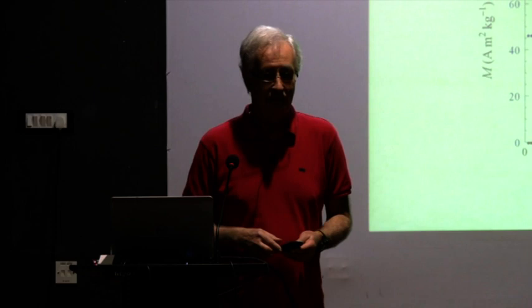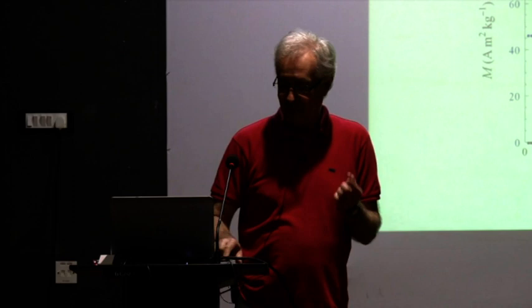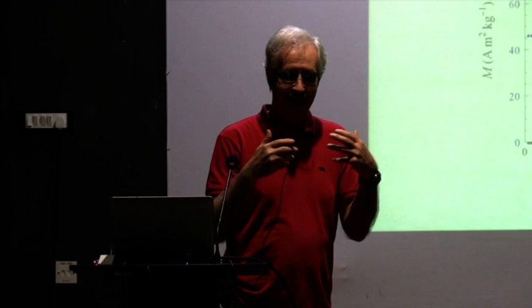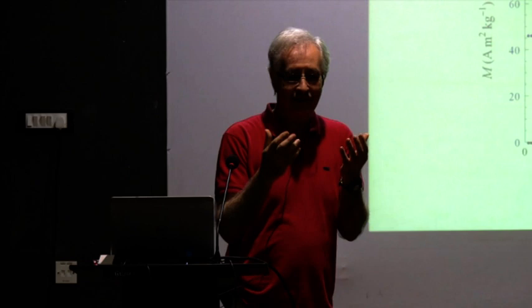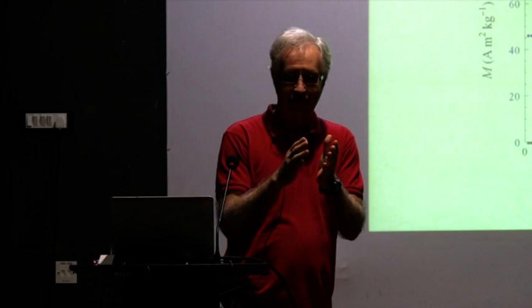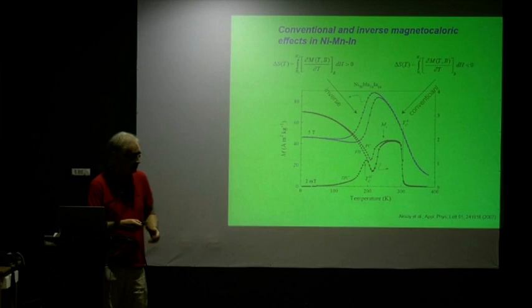And the inverse magnetocaloric effect is therefore the observation of the cooling tells us directly that the classical additivity of the different components does not work when you are at a transition, because at a transition you're not at a fixed thermodynamical state. You're in mixed states, you're going from one state to another state. You have hysteresis here. What do we mean by hysteresis?